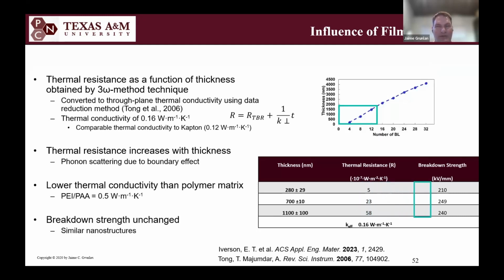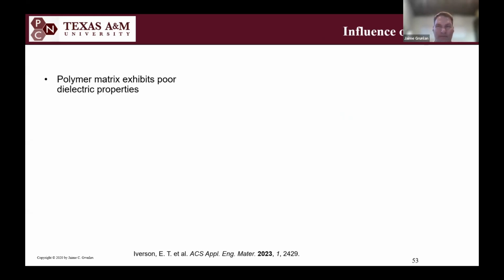So that's kind of weird, interesting. It's because it's such high density. But then if you look at the breakdown strength, so we had 0.16 watt per meter Kelvin, and we have a breakdown strength that's also very similar to Kapton, on the high end of Kapton. So we have the high end of Kapton's thermal conductivity and the high end of Kapton's breakdown strength, but this is a water-based coating technology. So that was kind of a fun thing.